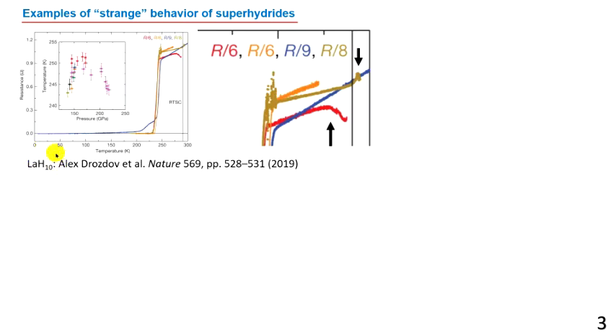Let's look at lanthanum H10, Figure 1 in the publication of Alex Drozdov and co-authors in Nature in 2019. We can see several temperature dependencies of resistance. Two out of four of these resistance dependencies have some features: a downturn feature in the red curve, and this jump in the resistance shown by the arrow. It's definitely not normal, definitely anomalous behavior of resistance.